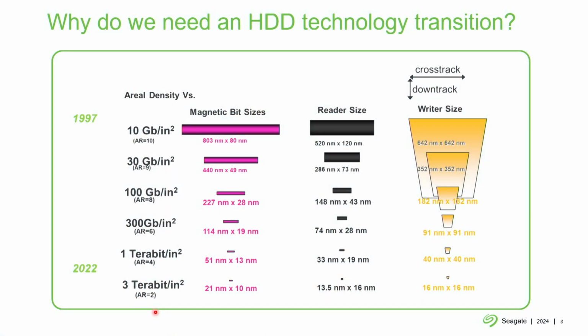So there are all of these technological leaps that were necessary in order to enable these significant reductions in geometry size. Now if we look at 3 terabit per square inch, which is kind of where we want to be close to the end of this decade, we're talking about bit sizes that are 20 nanometers at the largest dimension, which means I need a writer that's 16 nanometers wide and a reader that's 13 nanometers wide. The problem is if we stick to perpendicular magnetic recording, which means that I'm using magnetic writers to write the information, if I make these writers very, very small, then I lose the magnetic field that's available. So going to very high areal densities is just not possible with the current technology.